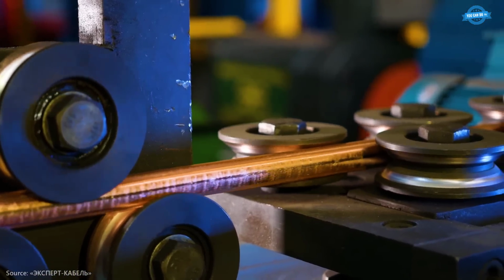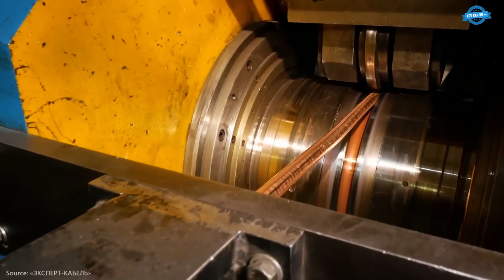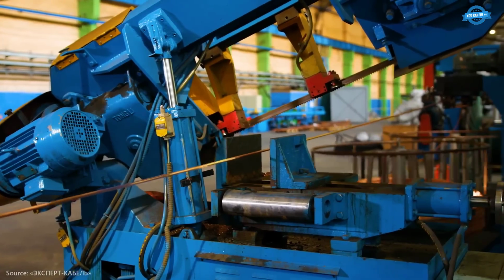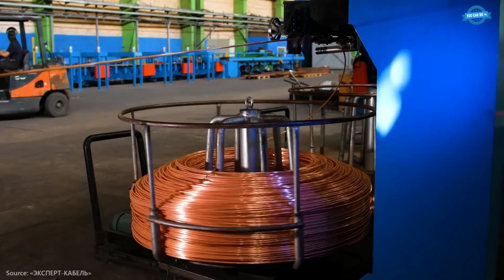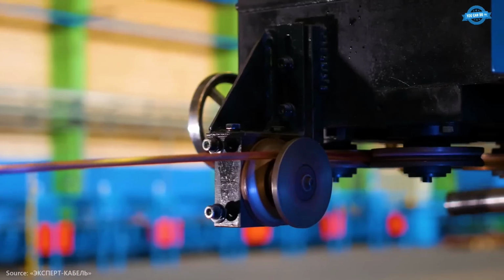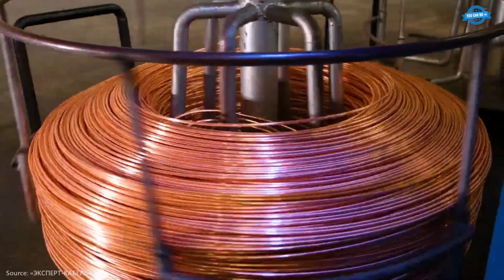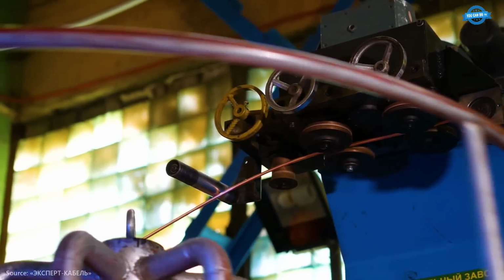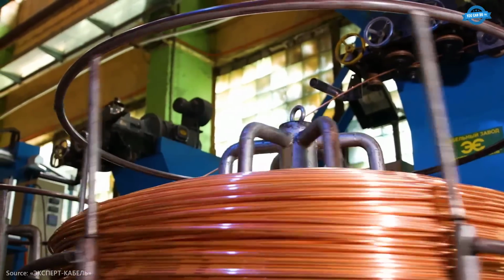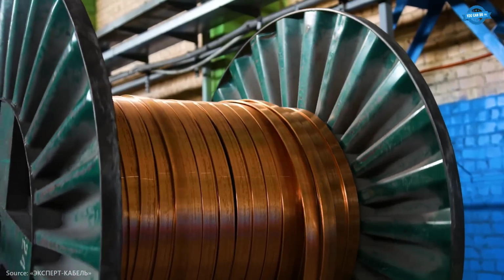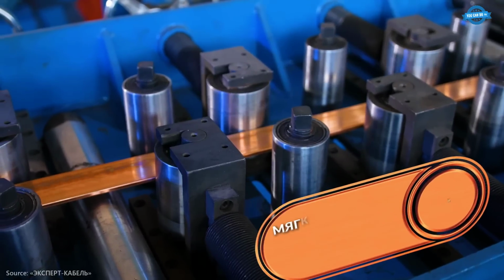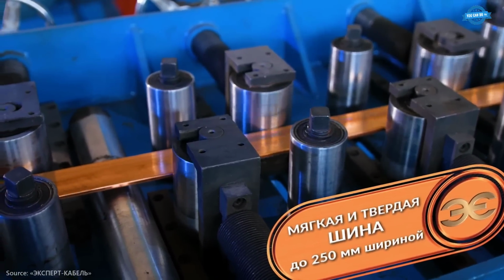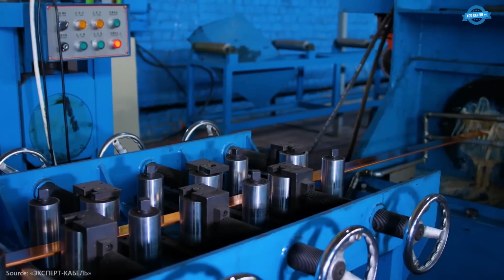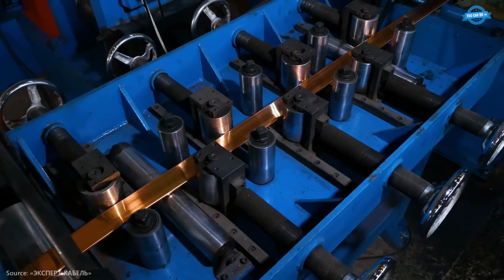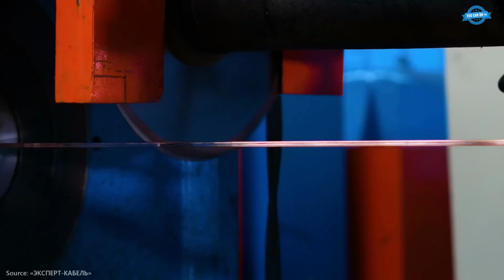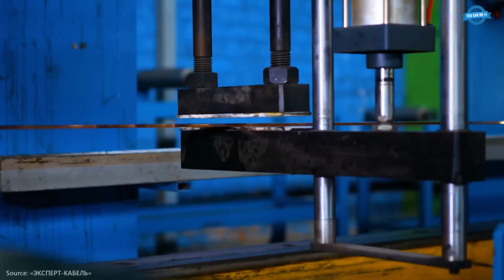Each coil has an internal diameter of approximately 700 millimeters and an external diameter of 1,450 millimeters. Finished products are secured with plastic straps, wrapped in polyethylene, and placed on wooden pallets. Oxygen-free copper rods boast stable chemical composition and high electrical conductivity. With oxygen content below 2 ppm and minimal gas porosity, the risk of cracks in cast and rolled products is significantly reduced.